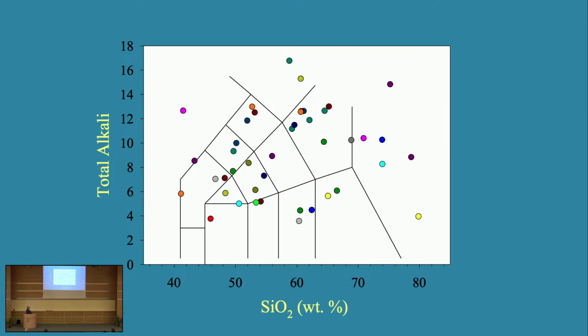And what you can see here is a selection of just 2 of those elements, total alkalis versus SiO2. SiO2, extremely important, extremely variable, going from 40% to 80%. So from a technical point of view, one sentence, and then I'll answer your question. We're going from the contents of silica in slags, which are produced by iron making and so on, all the way up to the content of SiO2 in good glass forming processes. So we're going from the metallurgical extraction industry to the glass industry in the range of what the Earth gives us.